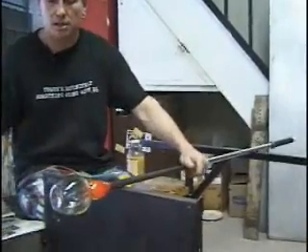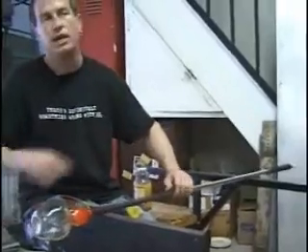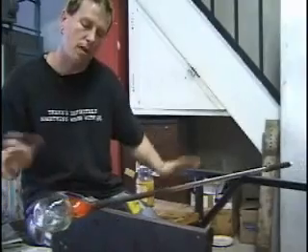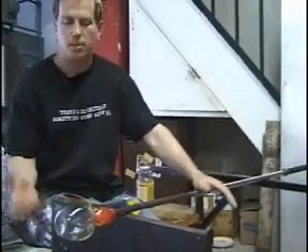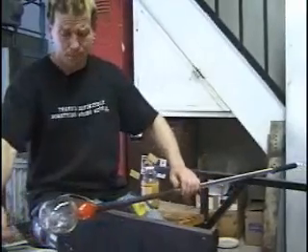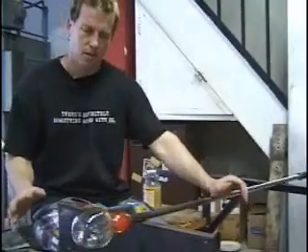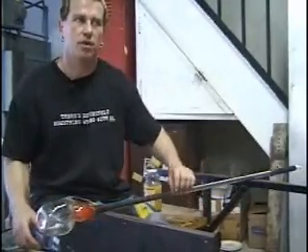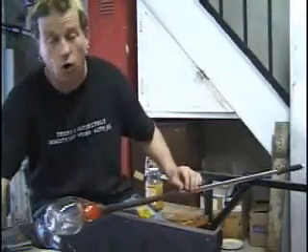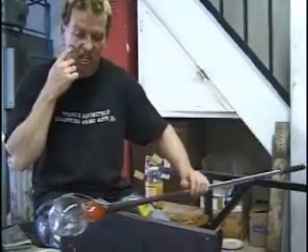So now the piece is still hot. It's got some motion in it. He's going to make the punty for me, and I just have to kind of babysit this. I got to keep it warm, but not too warm. It has to be cool enough that I can get it to crack off, but not break. When you punty up and when you take the punty off at the end is probably the most common time for the piece to fail, for it to crack, to hit the floor, to pull a little hole out of the bottom. Just about anything can go wrong in that transferring stage.